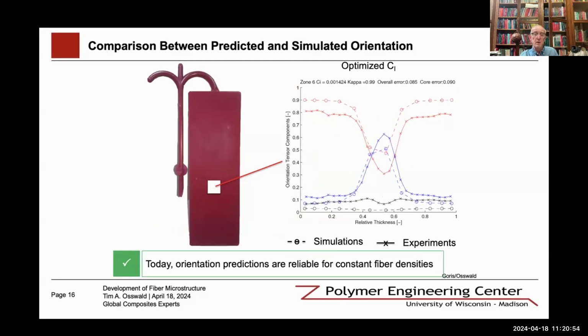There are still some discrepancies, but one of the things that the model assumes is that we have a constant fiber density distribution. And as you saw, the fiber density in the center increases. So we have more fibers in the center or core of the part than we do in the skin area. And so obviously we will never be able to get to a very accurate representation unless we include the variability of the fiber density distribution during processing.